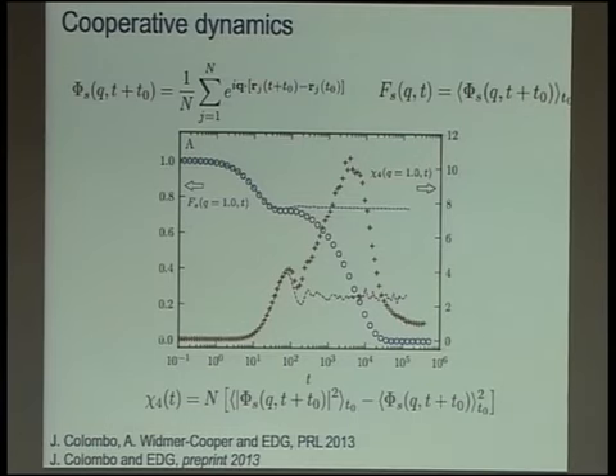And so when I look at this type of function, I do see, this is for a wave vector that is of the order, let's say, of the mesh size of the network. And so there you can see that actually the microscopic dynamics of this type of structure develops some interesting features that are, for example, very similar to what you would observe in a glassy system. So you have this plateau in this function that clearly indicates the presence of a localization process, after which then the relaxation in the particle displacement eventually decays to zero.